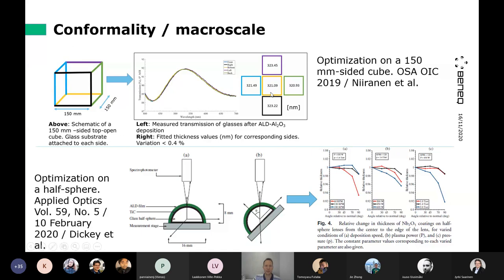And by comparing then the results after the deposition, we can see that the uniformity is very, very good. So these are film thickness in nanometers. And fitting these, we see that variation is around 0.4% for the thickness, which is quite amazing and certainly impossible to do with any other technique than ALD. Okay, there's a reference for that as well.